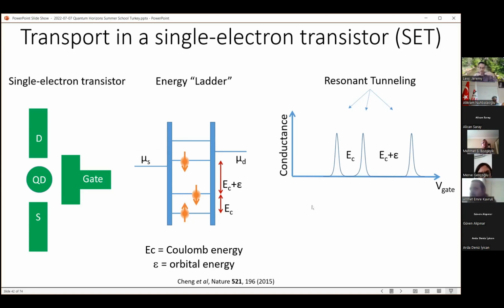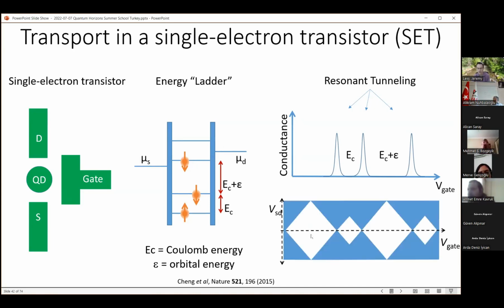But if you were to put a chemical potential difference, then it would be possible for this electron to hop onto the lower energy state, and now this is unoccupied, and an electron from the drain can go over here and so forth. So the general structure or features, if this is the vertical axis, is the source drain bias, and the horizontal axis is the gate bias, what you find is that there are sort of insulating regimes and conducting regimes. So the insulating regimes are the white regions here, these diamond features, and then the intersection points are where you go from n-1 to n+1 electrons.